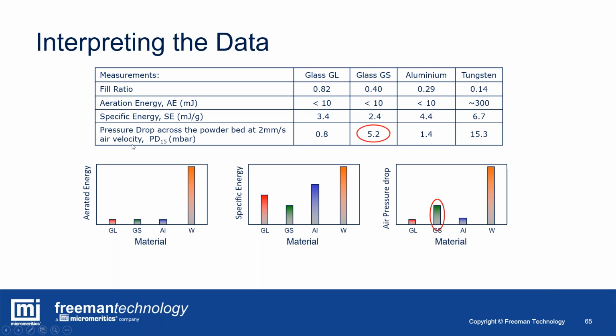And if we look at that pressure drop, the permeability data shows that the small glass beads has a pressure drop measurement of 5.2 millibars compared to 0.8, telling us it's about 6 times more difficult to get air to backflow through that material during the filling process.